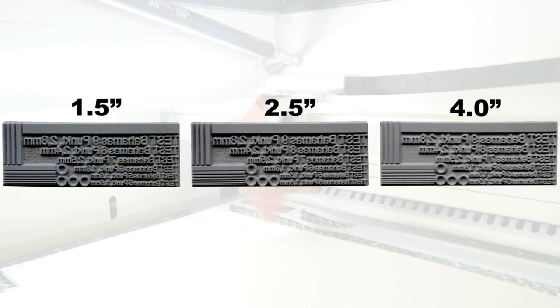In contrast with the test on anodized aluminium, we are not losing thinner lines here and the reason is that the engraving speed is so much slower when engraving rubber. The 2.5 inch lens is showing fairly good results and very good quality. However, if you would use an ink pad and stamp a paper, there is a clear distinctive difference between the 1.5 and the 2.5. The conclusion is the same as anodized aluminium: the smaller the beam spot size, the smaller and more detailed engraving we will get.